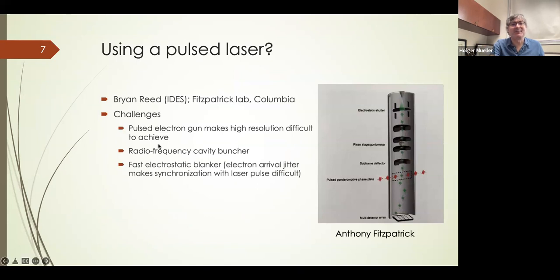One of the first ideas, by Brian Reed, who is now running a company called IDES Corporation, was to use a pulse laser interacting with a pulsed electron beam in a pulsed microscope. And this idea is now being picked up by the Anthony Fitzpatrick lab at Columbia University. But there are challenges that we noted when we started our project about 10 years ago. As many people in the audience know much better than me, pulsed electron microscopes don't perform quite as well as continuous ones. That's a first problem. And a second problem is we need to synchronize the laser pulses with the electron pulses very well, and that can lead to its own issues.